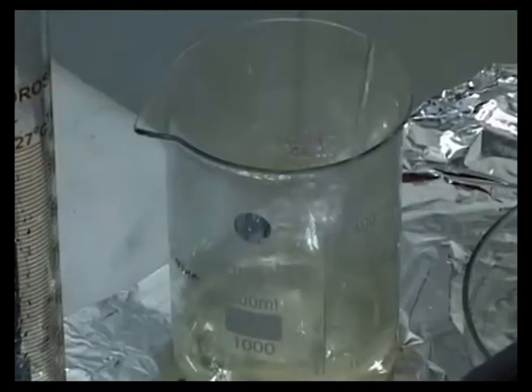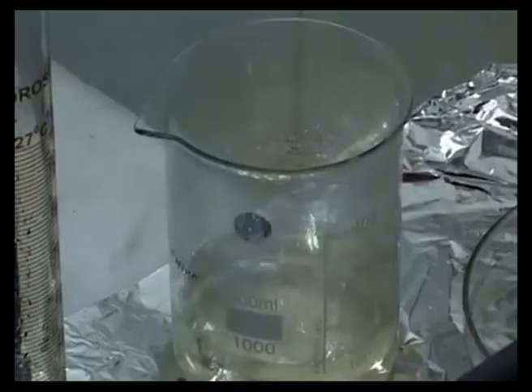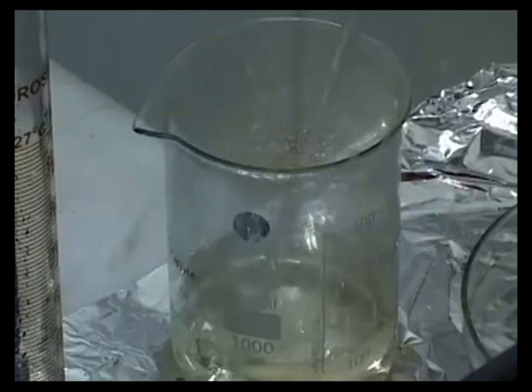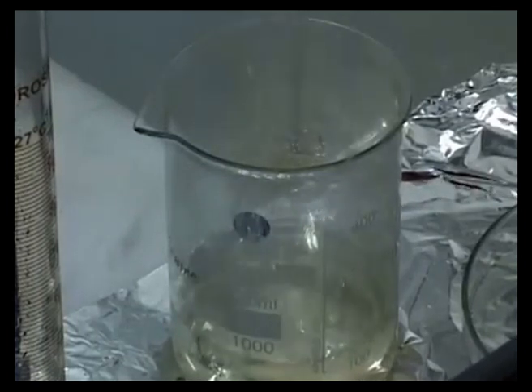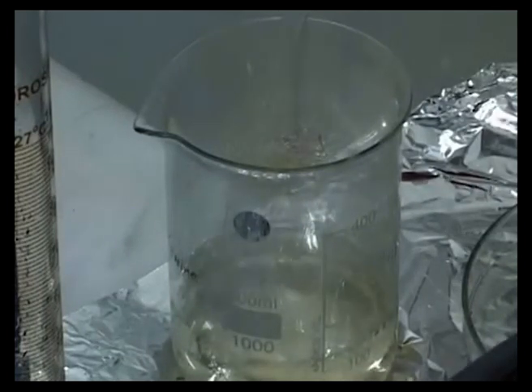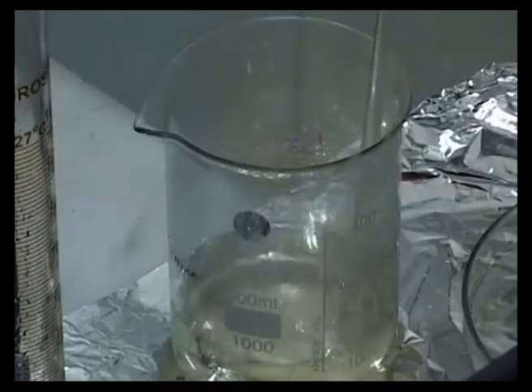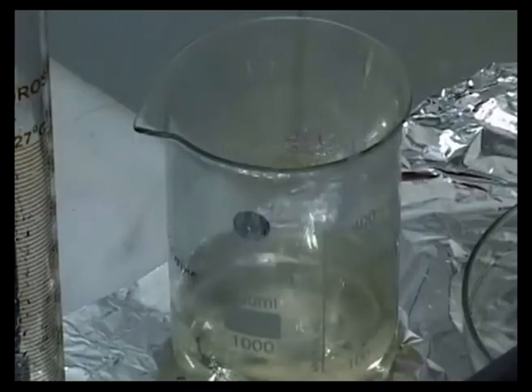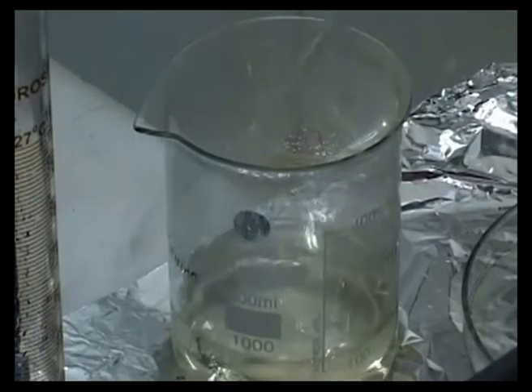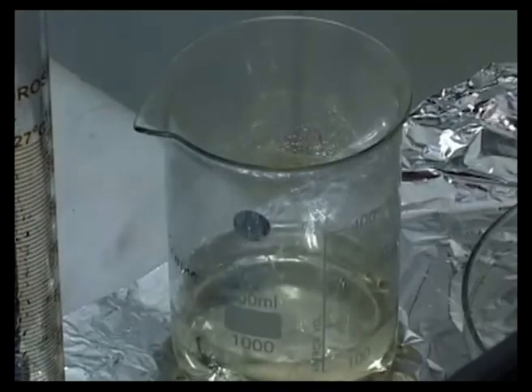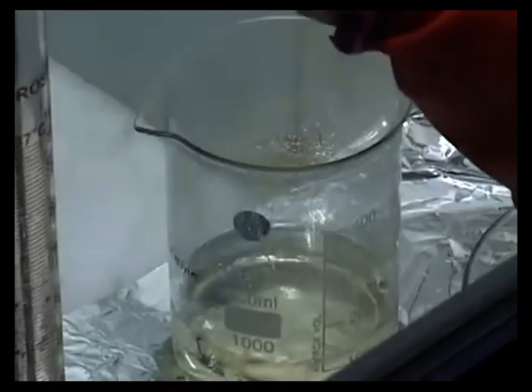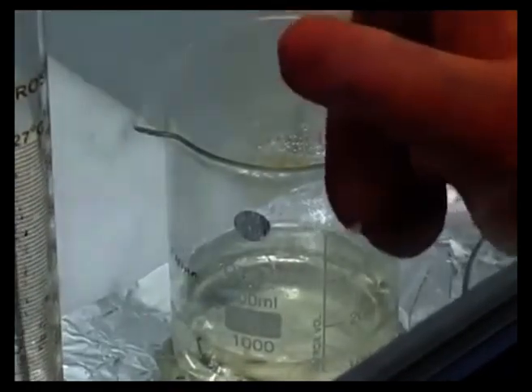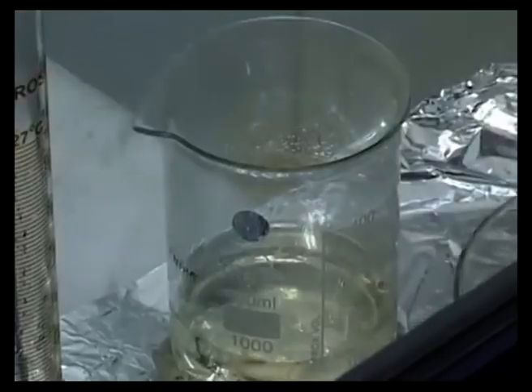This is a glass rod. You cannot really use any other metal rod for doing this because the acid immediately produces the salts from the metal, and it also deposits the metal and takes it off, and in the process gets contaminated. So you have to always use a glass rod or a glass container for doing this piranha making process. Once this is made, you rinse off the excess piranha on the glass rod and keep this rod back into the container for H2O2, and this would later on be cleaned before we can reuse this again.